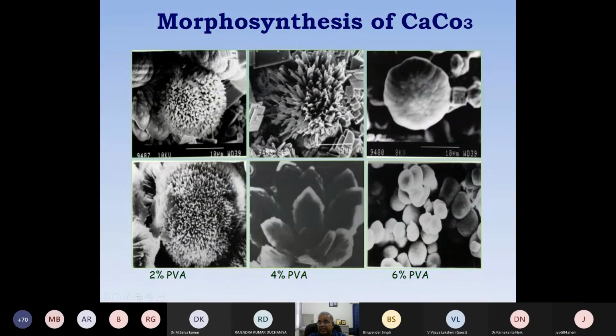If you synthesize in a conventional way, the calcite is the room temperature phase, the aragonite is formed around 50 to 60 degrees centigrade, whereas the vaterite is around 80 to 90 degrees centigrade. They are a bit high temperature products. But here everything we got under ambient condition around 30 degrees centigrade just by changing the polymer concentration.